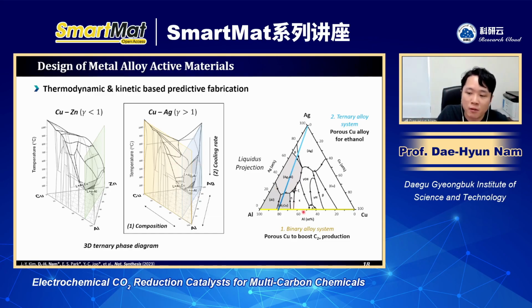In this way, first, we had to find the optimal copper structure, which can produce a lot of C2 products. So we started by designing the binary phase first. After we found an optimal composition, which can produce a lot of C2 chemicals, we started to mix silver into this composition. This enabled us to find an optimal point, which can control the selectivity between ethylene and ethanol. So I'm going to introduce one by one.